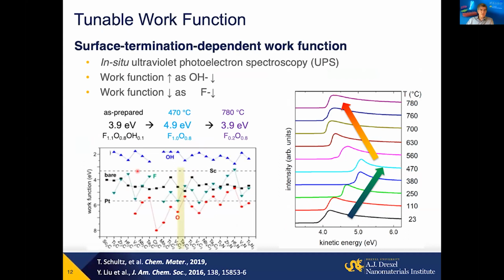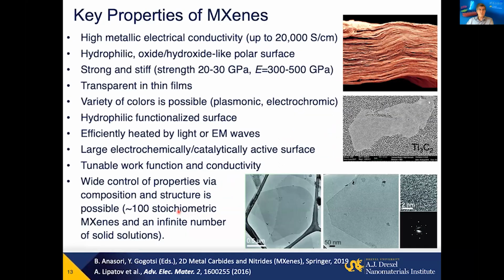And it's in very good agreement with theoretical prediction suggesting that OH groups take the work function to about 2 electron volts, and oxygen terminated Ti3C2 MXene will have about 6 electron volt work function here. So again, we learn how to control properties through surface chemistry.